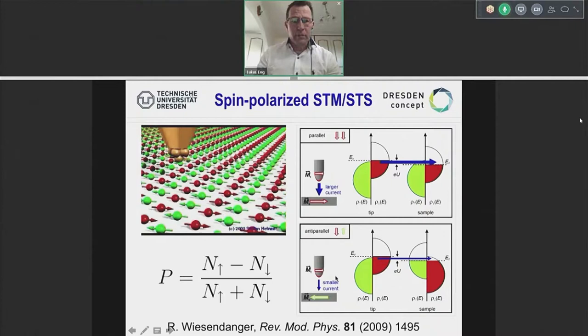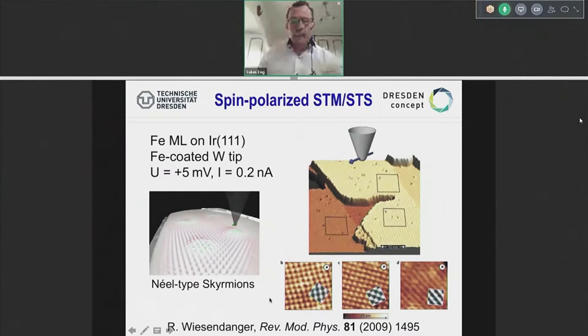That means exactly that you can fill states either with the right spin position or with the wrong spin position. In fact, this gives you the following cartoon. On the surface of iron, for instance, shown here as a monolayer, measured with a tungsten tip, you can nicely see how you can tunnel into or out of these states, giving exactly the spin structure like a Skyrmion. So, in fact, this is exactly what tunneling microscopy can do.